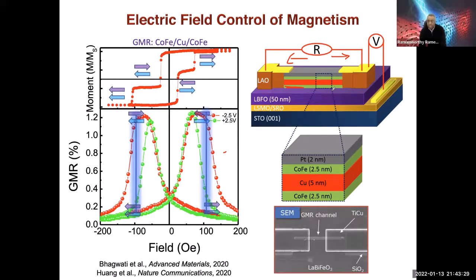You can actually see it in the symmetry of the hysteresis loop, Ramesh. With strontium ruthenate, when we use published values of the work function, it is larger, which I did not pay attention to for a while. It's about 5.1 eV, and there is a band offset. We have now done a lot of transport measurements, which show that indeed it is a Schottky barrier. With LSMO, what we did was to simply put different thicknesses. By the time you hit 3 unit cells, the symmetry of the hysteresis loop will start to change. This is the ferroelectric hysteresis loop.